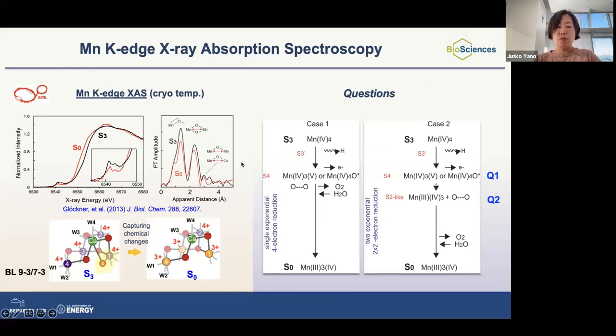For Photosystem II, what we want to look at is the last step where the S3 state goes back to the S0 state after molecular oxygen evolution and reset of the catalytic center. So at a synchrotron at cryogenic temperature, we see this kind of XANES changes. Basically, what we want to look at is in between here to here or here to here.